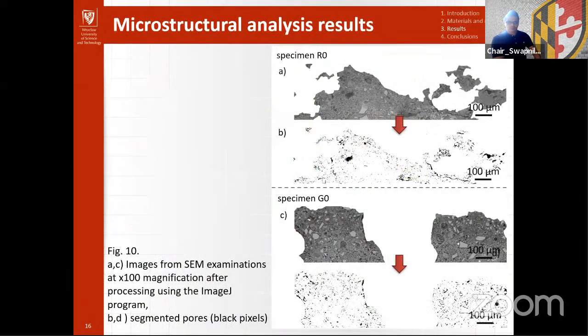We evaluated the microstructure of the samples using scanning electron microscopy. Figure 10 shows the cross-section of the sample's height at 100 magnifications. Analyzing the obtained data in ImageJ and Mathematica, we created images of segmented pores, which are shown in the graph as black pixels.